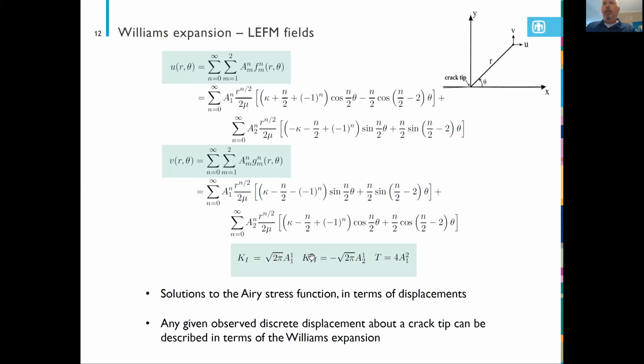So these Williams expansions ultimately arise from solutions at the continuum scale to the Airy stress function, which really describes the stress of a material under load and geometry. And with a little bit of information such as your shear modulus and the Poisson ratio, you can convert these to displacement fields, and note that these equations actually describe the displacement of any material surrounding a crack tip at that point. Ultimately, our stress intensity factors are described by these specific three leading coefficients, which I'm going to be referring to as the Williams coefficients from here on out.